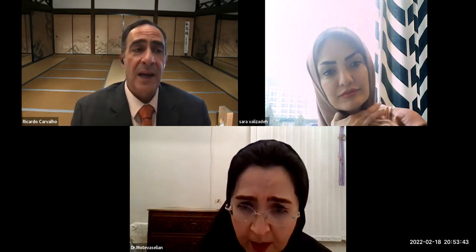So what do you advise for these patients in the posterior area that have not enough tooth structure and adequate space? Of course, the best you have for these cases is gold. If the patient does not accept gold, I would eventually try with zirconia. I agree with you that zirconia might be an option, because we already know that lithium disilicate will not work in a very thin prep. If I have to anticipate, I would say that with the monolithic zirconia, you will still need at least 1 millimeter thickness. That's my guess.